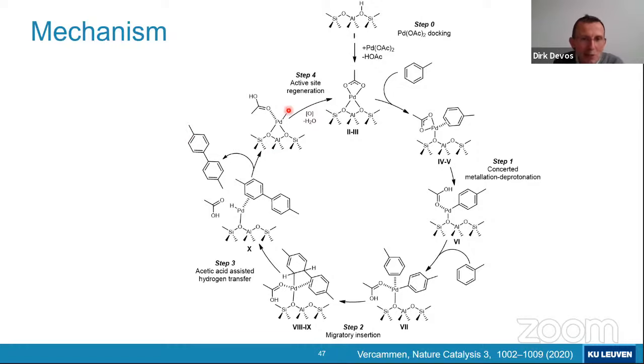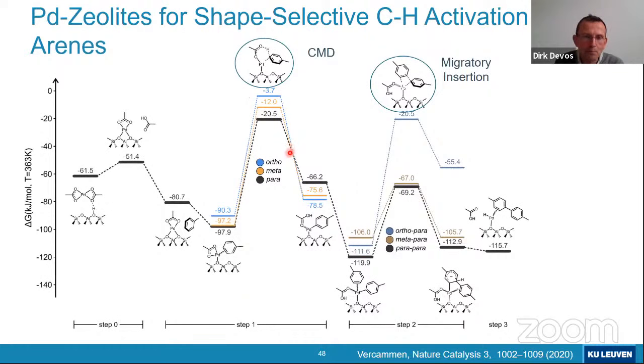Finally, we still need to reoxidize the palladium. I would consider this is not too difficult. If you do 400 turnovers, there is not too much evidence that the reoxidation of the palladium, maybe a hydride, is problematic, but we assume that this is actually quite a fast step.